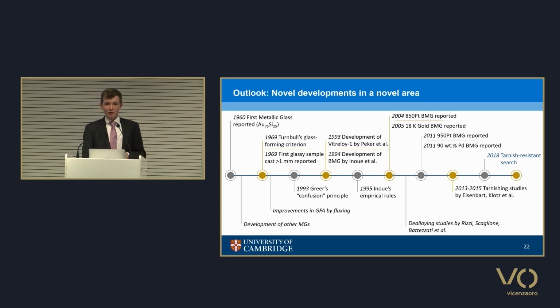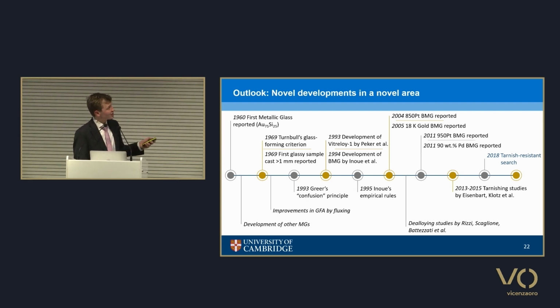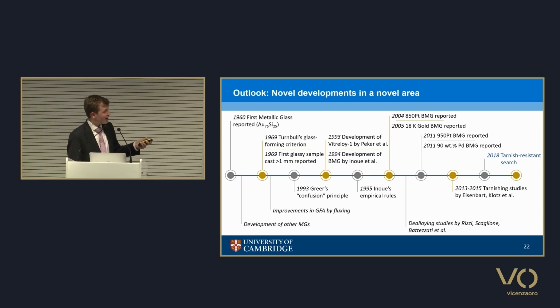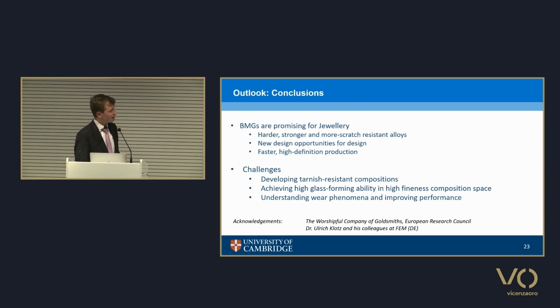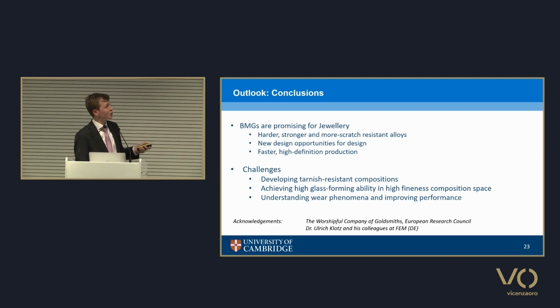So in conclusion, we've come quite a long way in metallic glasses. We started off in the gold system in the 1960s. That was over at Caltech. And in the 60 years since, we're almost at the point of hallmark-compliant bulk metallic glasses. Going forward, we've got these harder and hopefully more scratch-resistant alloys in many cases, but not all. There are new design opportunities, and there's also the case for faster, higher definition production that could rival technologies such as MIM. Unfortunately, there are still challenges to go, and that's largely about developing these tarnish-resistant compositions, achieving high glass-forming ability with high fineness, and also understanding the wear phenomena.